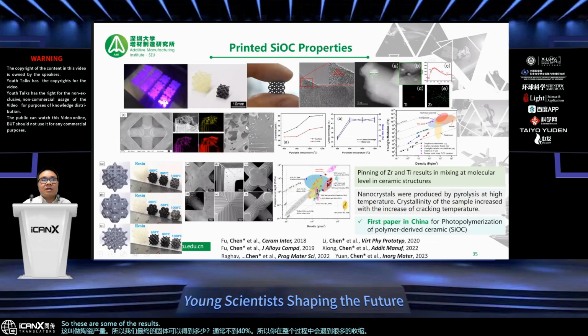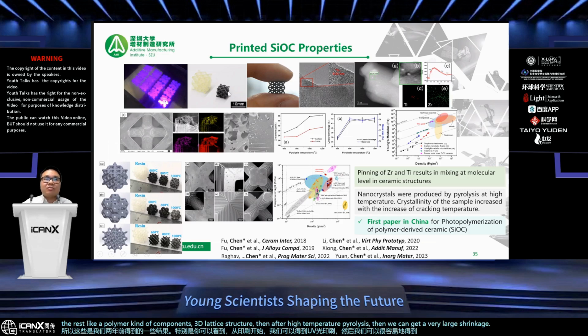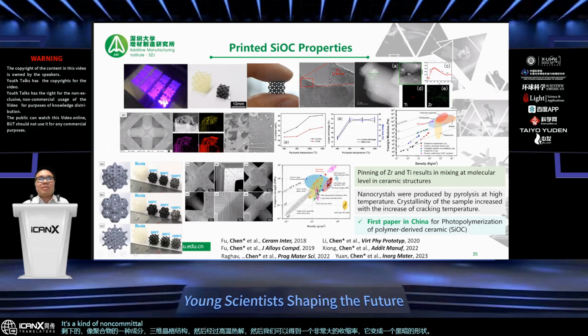These are some of the results we got two years ago. Starting from the UV light printing, we can very easily get red polymer components, a 3D lattice structure. Then after high temperature pyrolysis, we get very large shrinkage, and it becomes dark. So it's a non-conventional ceramic composition. We have SiOC or zirconia OC and so on. These structures are not the same as the oxide structures we produced earlier with cordierite or even SiC and so on.